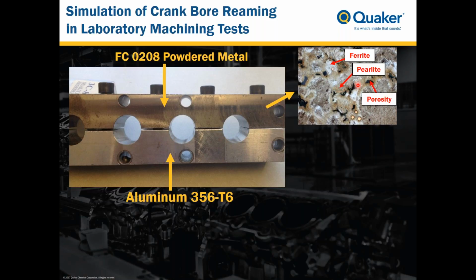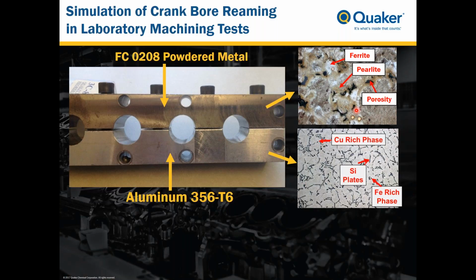And then very characteristic of powdered metals, you can see a high level of porosity, which is the black region. And these areas of porosity also present some unique challenges in machining. And then the bottom piece, again, is a high silicon containing aluminum, cast aluminum, and the microstructural features of this material are shown. Again, very characteristic. You can see the copper-rich intermetallics. You can see the silicon plates characteristic of these high silicon containing alloys, as well as the iron-rich intermetallic pieces.